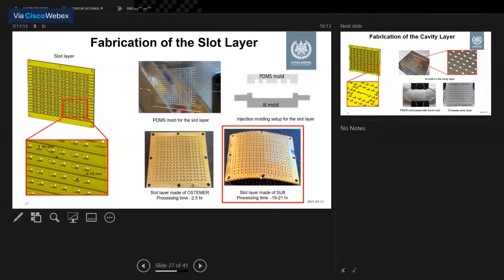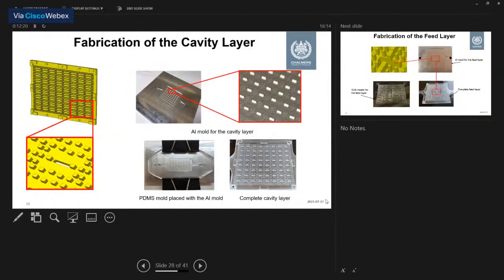Flat, and the SU-8 process, the SU-8 slot layer fabricated by SU-8 has a bend. If you compare the processing time, you can see it's only 2.5 hours to fabricate a slot layer by this injection molding method, whereas to fabricate a slot layer by this SU-8 photoresist is very long. Processing time is very long. By following the same method, we fabricate the cavity layer.